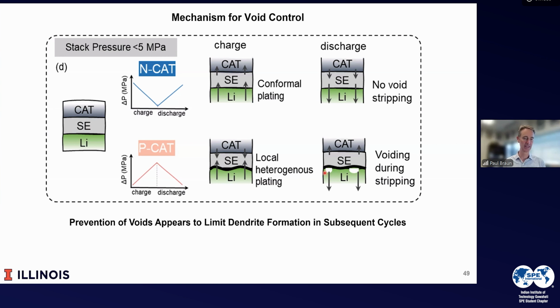And once you have a void, in the next cycle, you're likely to have a dendrite. So I think that controlling the chemomechanics both allows you to do a high current density discharge, which is high power, that's important, and it allows you to do high current charging without having dendrites because you don't create those dendrite initiation sites.